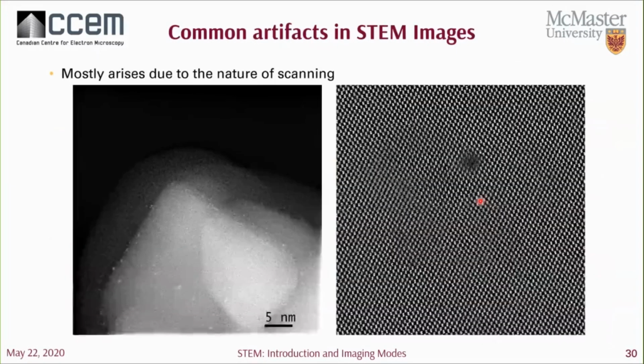So some other artifacts that you could see in STEM images. Some are due to the fact that we have a probe, you're subjecting a relatively large amount of energy into a small area. So you can have beam-induced contamination on your sample, or actually create a hole in your sample.